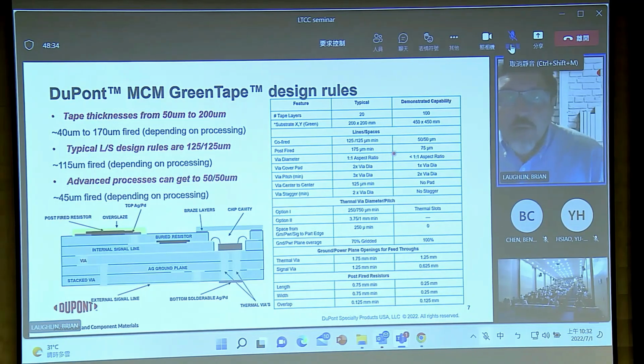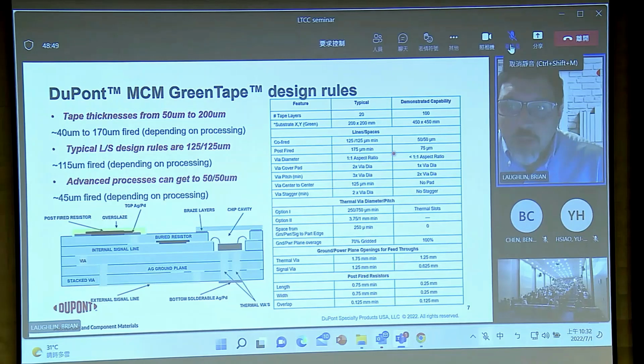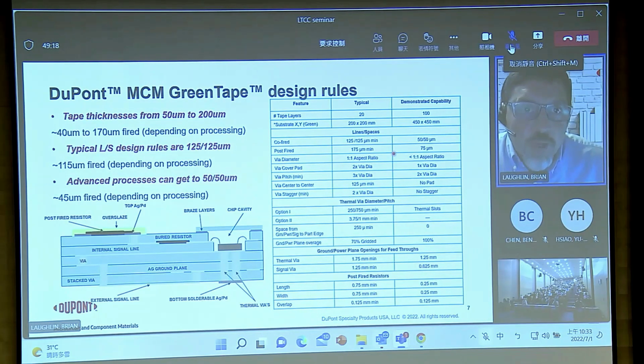And then to talk about the design rules of what you can do with those products. There's a whole list of design rules that have to do with how big of vias you can make and how close they're spaced together, and XY printing design rules. I'll leave these charts here that I'm sure will be provided as you need or on our website. But I'll say, putting it into generalities, we have tape thicknesses from about 50 microns to 200 microns. We can probably go thinner than that. We can definitely go thicker than that. Because the material shrinks on firing, your design thickness is somewhere around 40 microns to 170 microns per dielectric layer. Our typical lines and spacing design rules are about 5 mils lines and spaces, or 125 microns. But again, because there's shrinkage, it's more like 100 microns.